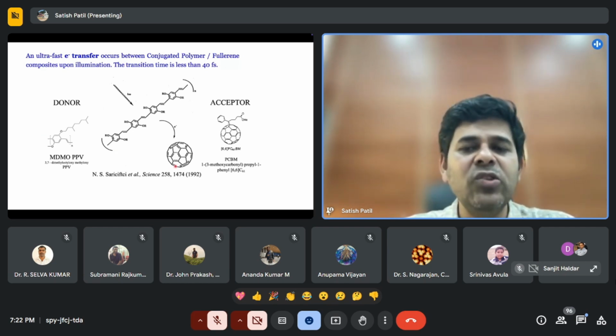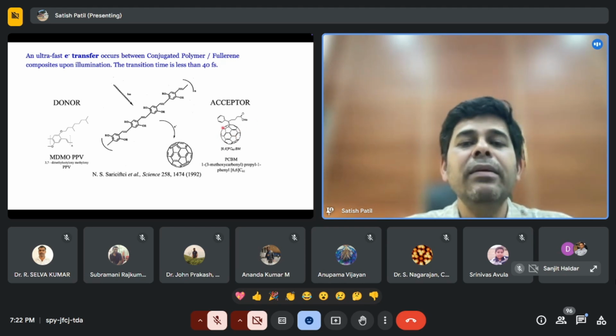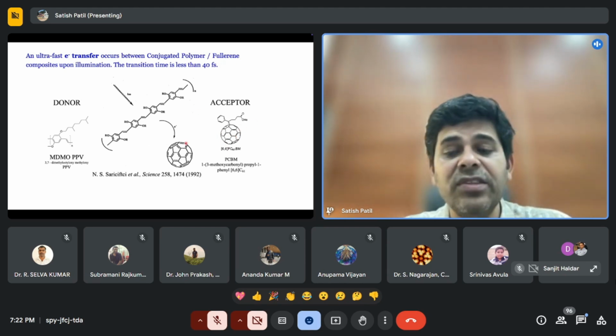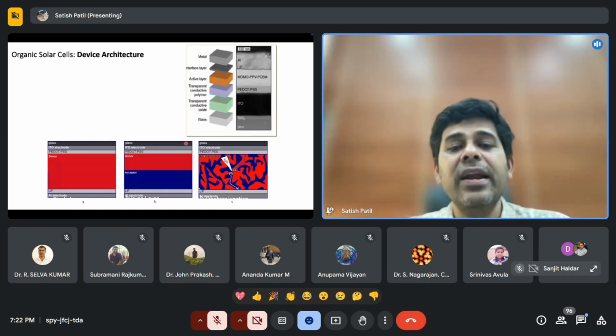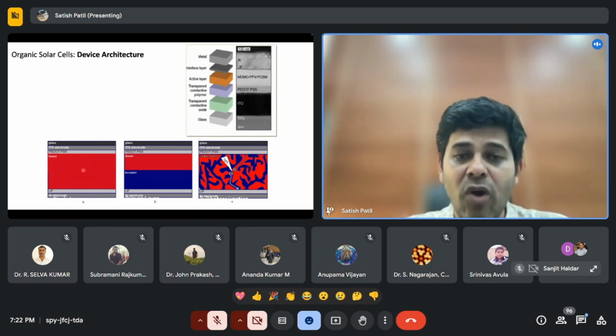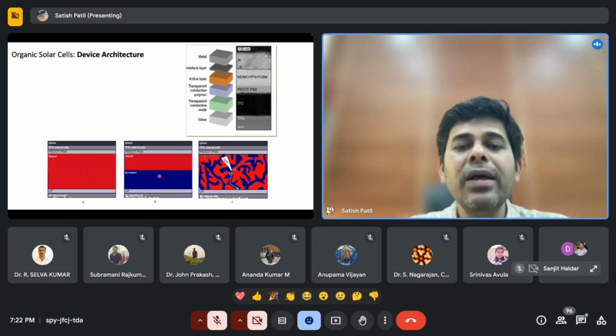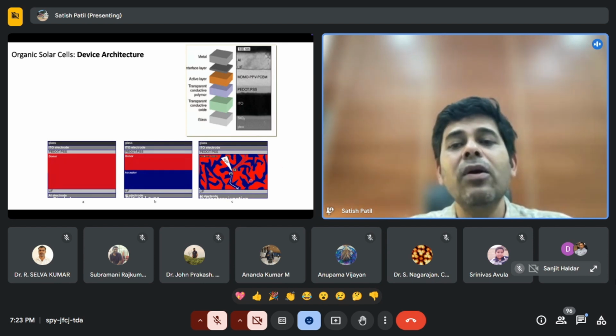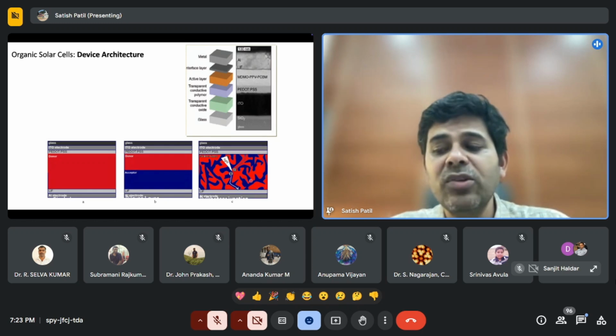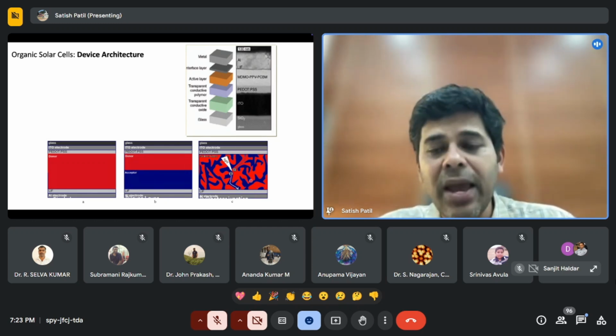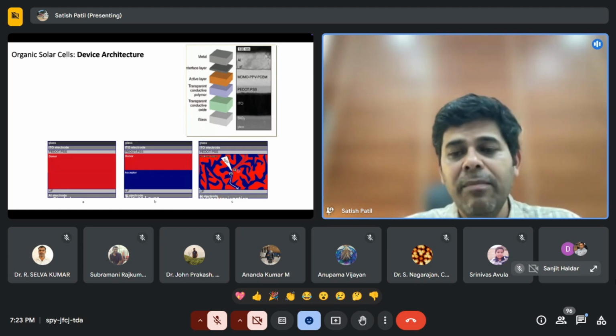And eventually, fullerene is insoluble. You can see that they introduced the alkyl chain and made PCBM. Fred Wudl in Santa Barbara synthesized PCBM, and now people are using soluble PCBM here. This is a derivative of C60. And then you see the device efficiencies improve dramatically. And this is where the current device architecture comes in: a single layer does not work by sandwiching in the electrodes. A bilayer gives a slightly higher efficiency, but by mixing them together, something called a bulk heterojunction, bulk heterojunction solar cells give a very high efficiency. For example, this is a material.